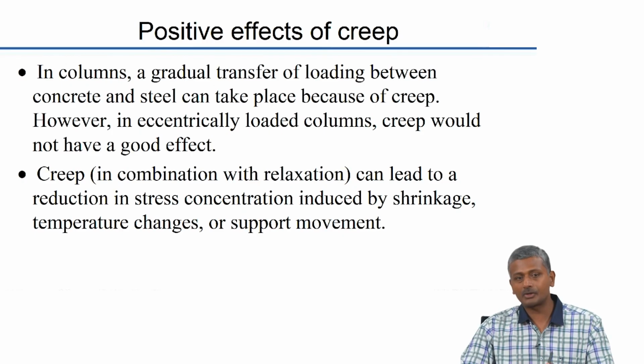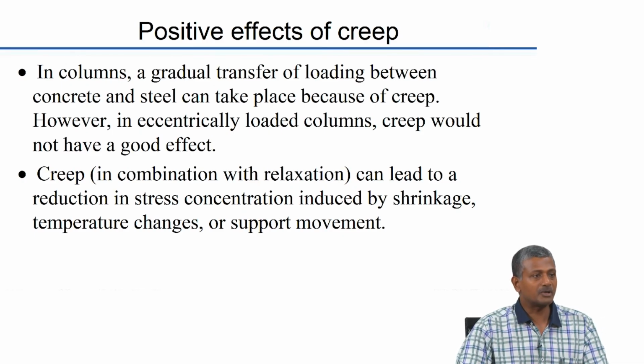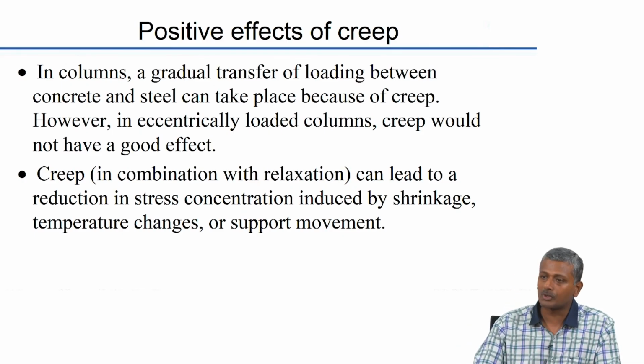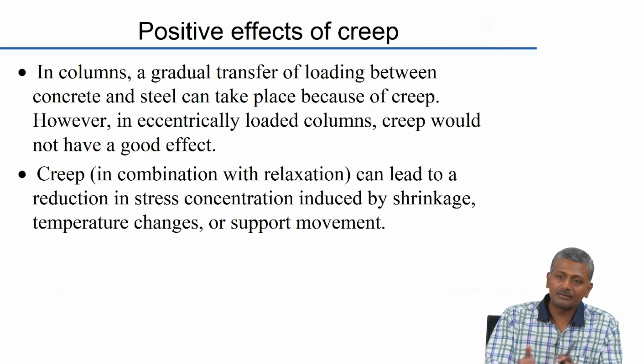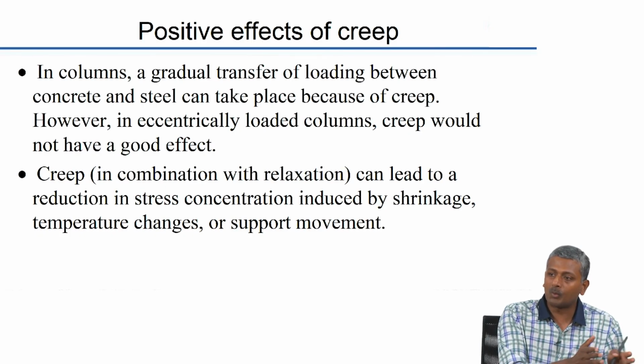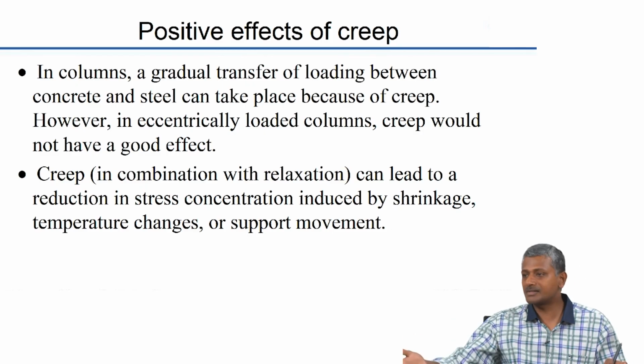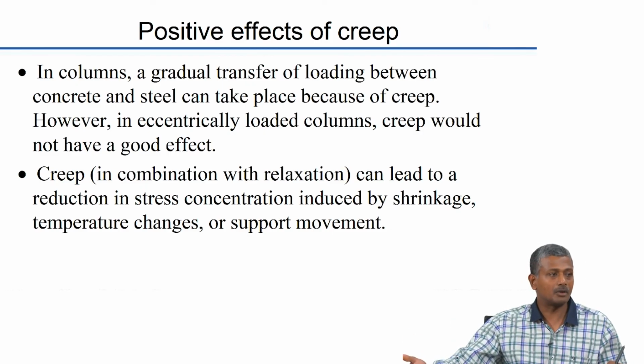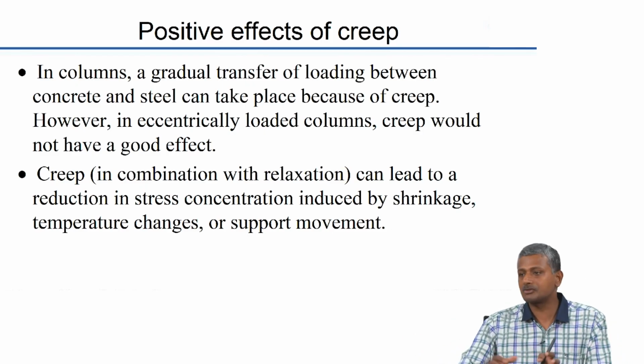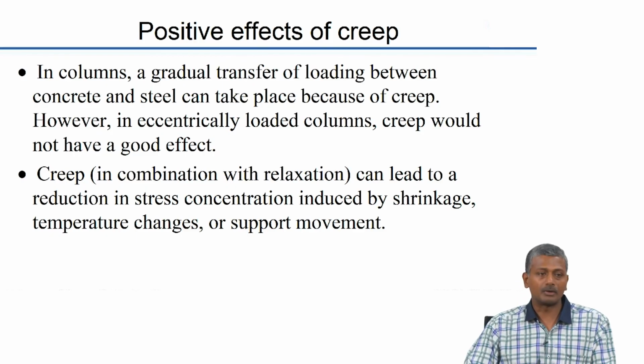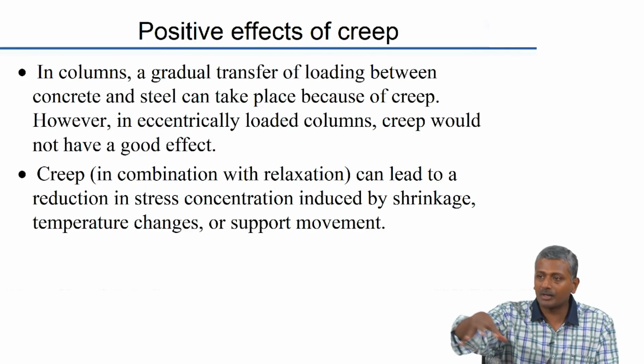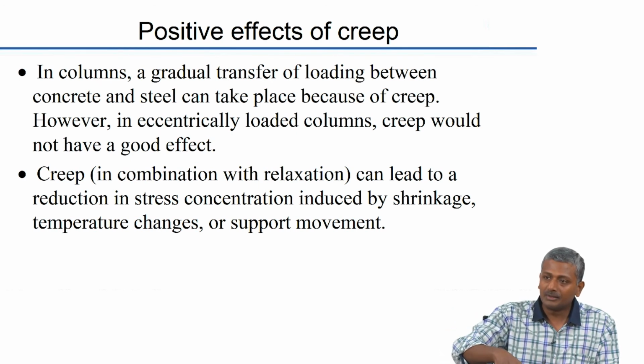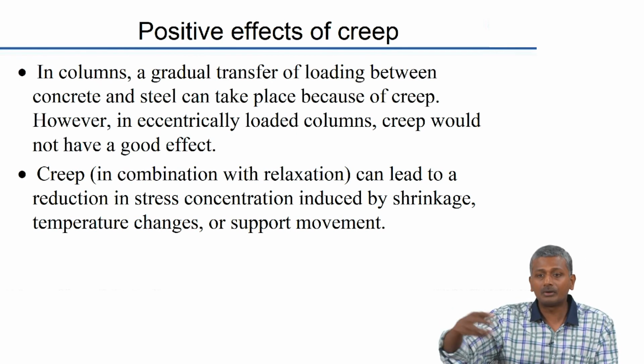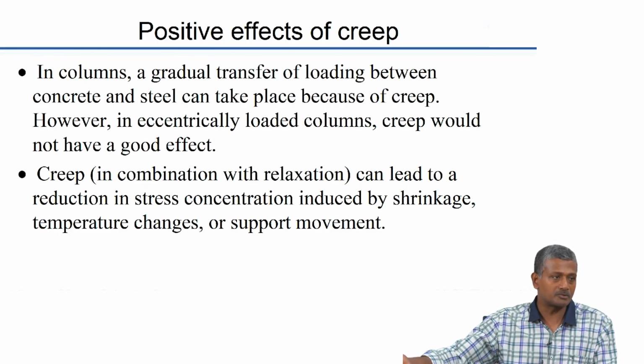In regular columns it is alright, the transfer can be alright, but in eccentrically loaded columns what you will do is you will probably solve the problem in one part of the column, whereas add to the problem in the other part of the column, because you get different combinations of loading in different parts of the column. So, depending on where you are in an eccentrically loaded column, you can actually get a situation that is better than the no creep situation, or a situation that is worse than the no creep situation.